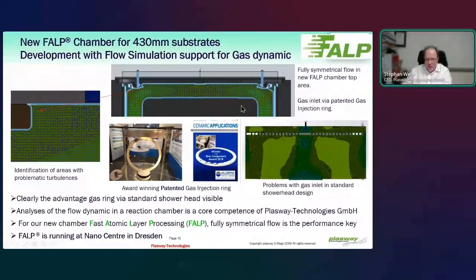And by the way, some people are still using this old-fashioned shower head design for bringing in the gases. You see here directly the problem when you make flow dynamic simulations of this gas shower head, because a special room is needed between the shower head and where the gas is coming out. You have here really a dead volume. And if you don't create the holes inside the shower head perfectly, you really don't get just laminar flow downstairs. So you have an intrinsic non-uniformity.